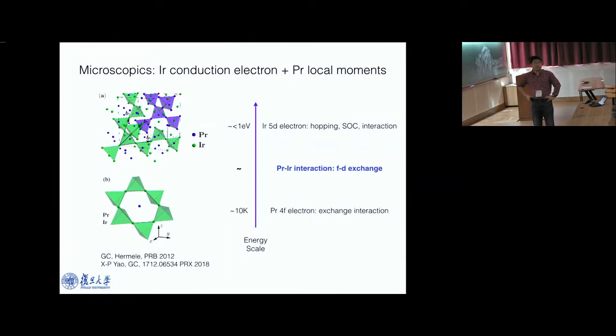So the dominant energy scale in the problem would be the conducting electron hopping, conducting electron spin-orbit coupling, and the correlation between them. And the lowest energy scale in the problem would be the exchange interaction between the local moment. That would be like 10 Kelvin. In between, there is a so-called Kondo-like coupling between a local moment and a conducting electron. So this is what I call f-d exchange.